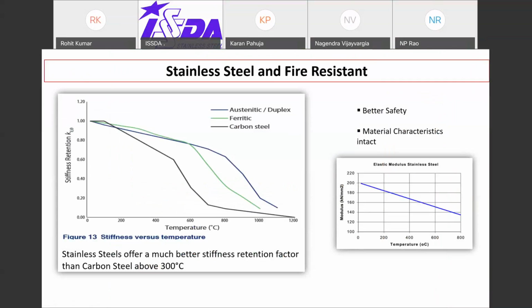Impact was a property. Fire is also a very important property. Say for this stiffness retention factor versus temperature graph, if you compare austenitic, duplex stainless steel and carbon steel, the bottom line is the carbon steel, and the other two are stainless steel. So if you look at stainless steel, even at 600 degrees centigrade, it has retained almost half of its strength. Whereas in carbon steel, above 400 degrees centigrade, the strength falls very quickly.